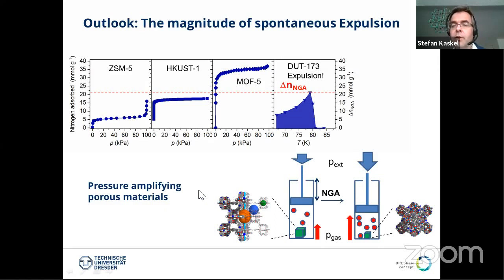And it means also that when you increase the pressure, the overall pressure is increased. So this is also a pressure amplifying material. And of course, we are still developing these materials further. And this is a material that is not published yet. It shows an NGA with nitrogen of more than 20 millimole per gram. So the expulsion is extremely high. And here we compare this with traditional materials like HKUST-1, ZSM5, zeolite, and MOF5. And we see that it's of the same magnitude or even higher as compared to reference MOF materials. So it is quite a remarkable effect and interesting what switchable materials can do.